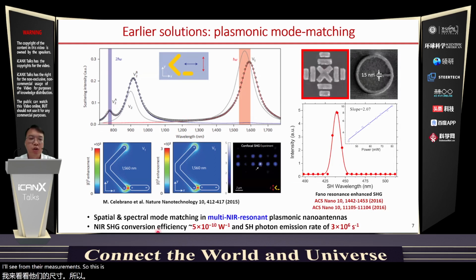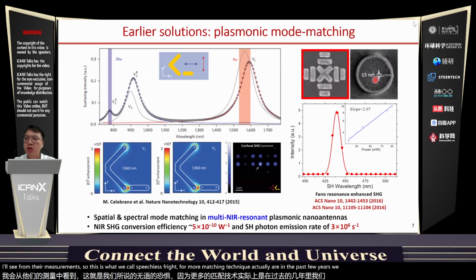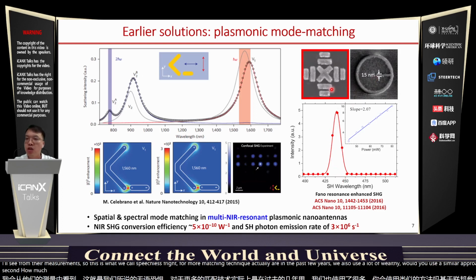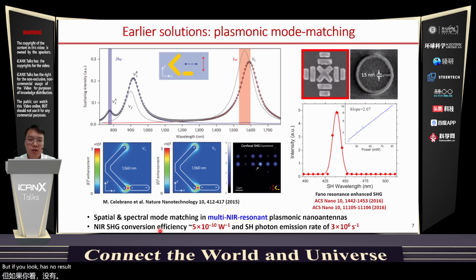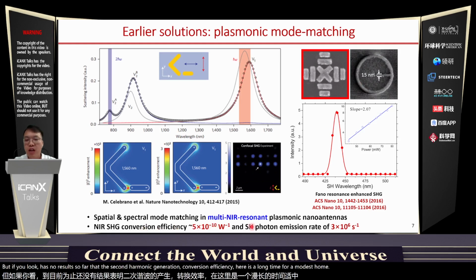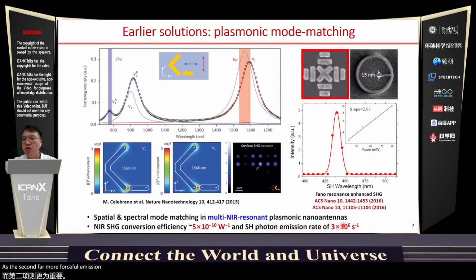So this is what we call the spatial and spectral mode matching technique. In the past few years, we also used a similar approach based on Fano resonance to enhance the second harmonic generation in those coupled plasmonic nanostructures. But if you look at their results, you find that the second harmonic generation conversion efficiency here is around 10^-10, and the second harmonic photon emission rate is on the order of 10^6. Please keep in mind these two numbers, because later I will show you that with our new method, we can increase these two numbers by more or less 3 orders of magnitude.